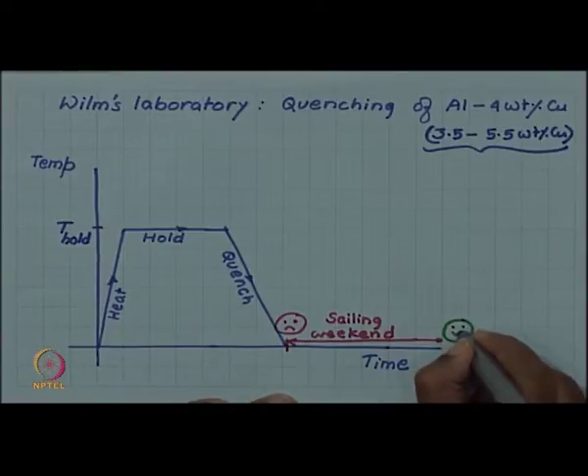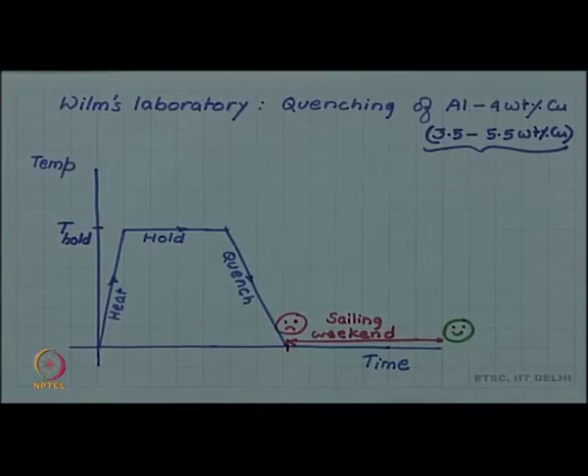So finally, his research was successful. He found a way of increasing the hardness. Hardness does not increase simply on quenching, but quenching and waiting. That is, as the time passes, hardness seems to increase. He didn't have an explanation, but experimentally he could prove that hardness is increasing as a function of time.